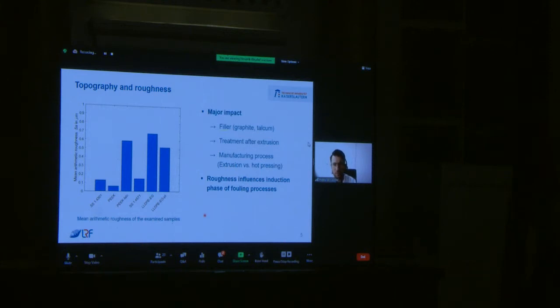A non-invasive confocal microscope was used to determine the roughnesses, and the figure here shows the mean arithmetic roughnesses of the investigated materials. And the greatest influence on the roughness is based on the use of fillers. But a plasma treatment, for example, can decrease the roughness again. Pure or unfilled PEEK has by far the lowest roughness.